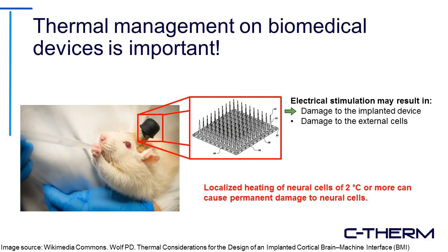accumulation inside of the probe, but it can also damage the external cells, because localized heating of neural cells of around 2 degrees or more can actually cause permanent damage to neurological tissue, either through the forming of glial scars in neural tissue, or through death of the material and the actual neurons that you're actually trying to measure from.